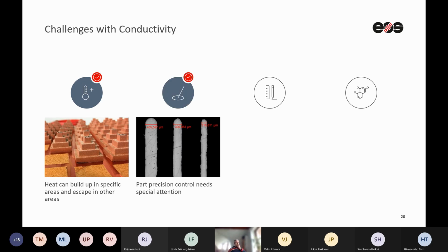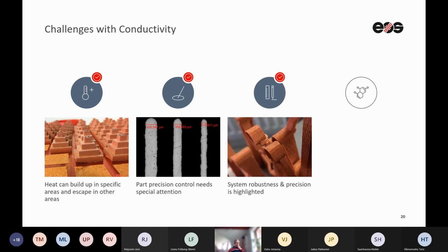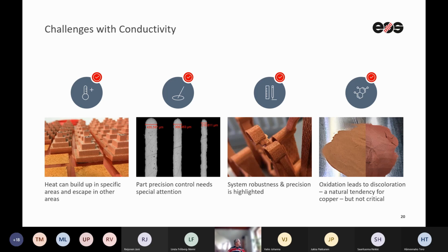Also, the melt pool size of copper processing: although you have the so-called nominal laser spot size, which might be 80 micrometers, in some cases you draw a line, and because of the high conductivity, the line width will be multiples of this nominal thickness. Also, copper being a relatively soft material, you have to design the jobs in a way that no distortions happen because of the inevitable forces in the build process. That is also a challenge. Also, the oxygen pickup of copper, which usually is only on the surfaces, the powder particle surfaces, can be significant, but usually not very dangerous.